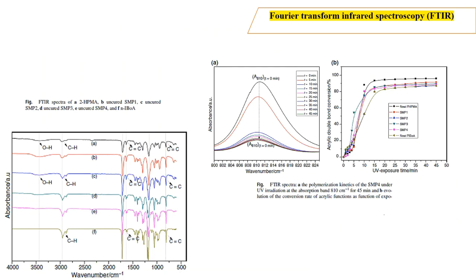Then the analysis was performed using infrared spectroscopy. The spectra of both samples show the acrylic double bond C=C, especially in the bands at 810 and 1636. These two absorption bands can be used to describe the polymerization process and evaluate the conversion of acrylic double bonds in the resulting networks. As you can see, all the samples show the same decreases in the concerned absorption bands. A very small intensity is observed after 45 minutes, corresponding to a negligible amount of unreacted monomers.